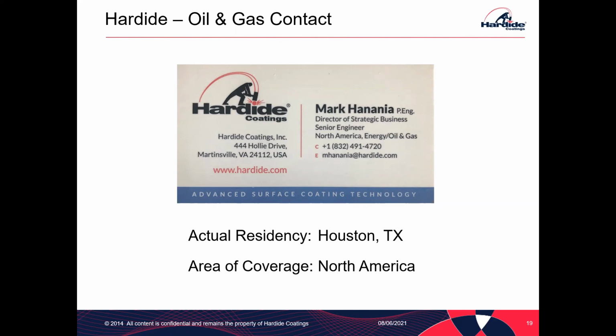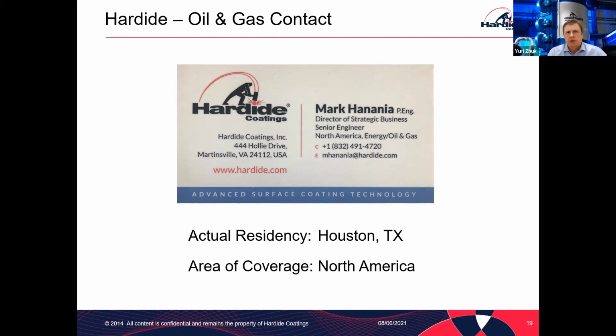Is the nickel layer always needed as an interlayer? Nickel is used as an adhesive sublayer, essentially a glue for our coating, providing maximum performance adhesion. It's not always required. For example, components made out of nickel or copper can be coated straight without any sublayer required. But we produce that nickel sublayer in-house, so that's a process we refined and practiced many, many times. Okay.